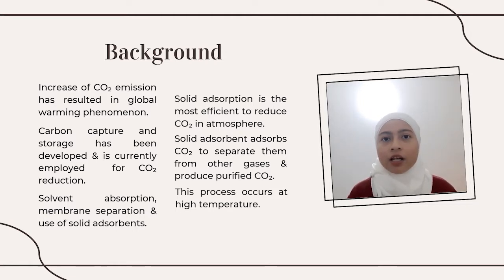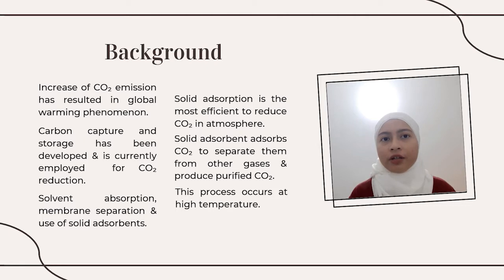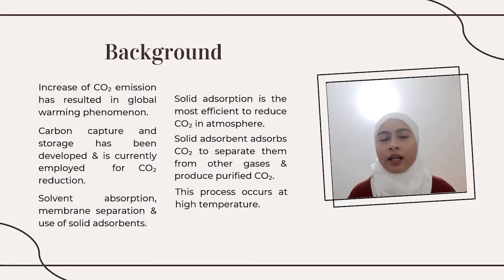Among these methods, solid absorption is reported to be the most efficient for carbon dioxide capture. It works by absorbing carbon dioxide to separate it from other gases in the atmosphere and purifying it. This process is usually conducted at high temperature in the range of 600 to 700 degrees Celsius, because calcium oxide absorbent can effectively absorb carbon dioxide and convert it into calcium carbonate within that temperature range.